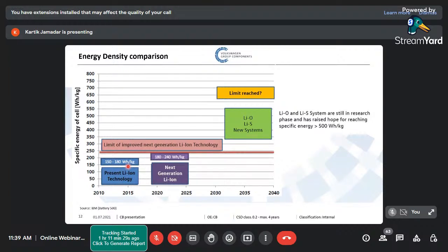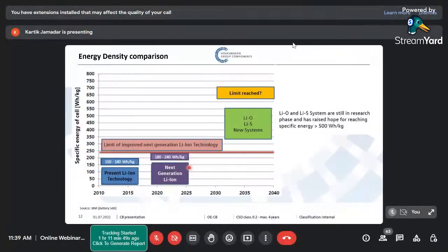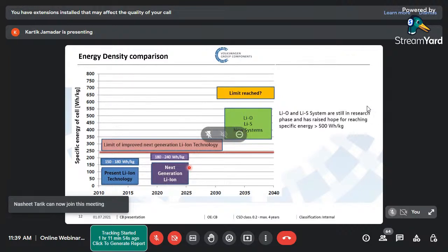And nowadays, more or less, we are talking about 811, 80% nickel, 10% cobalt, and 10% manganese. The tendency is to go towards 9, 0.5, 0.5, that is 90% nickel, 5% cobalt, and 5% manganese. So obviously, we would have to sacrifice some kind of safety in that. But at the same time, your BMS system should be sharp enough to get that voltage peak and should